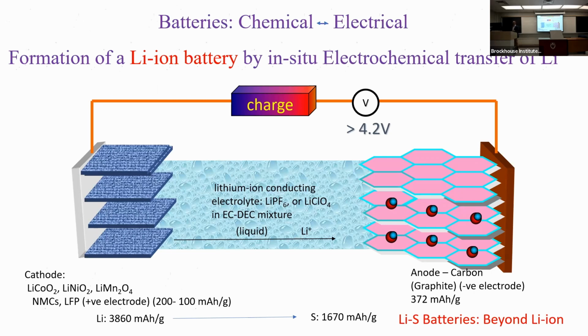So when a battery starts its life, the lithium is in the wrong place, it's in the oxide. And then by charging it, in a formation stage, you put the lithium into the carbon. As a result, the battery has the energy and the potential of 4.2 volts and has a certain energy capacity. Now, if you look at these figures here, the graphite anode carbon structure, graphite has an energy capacity.